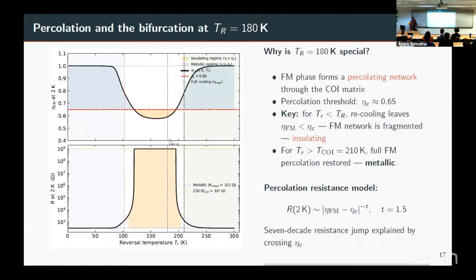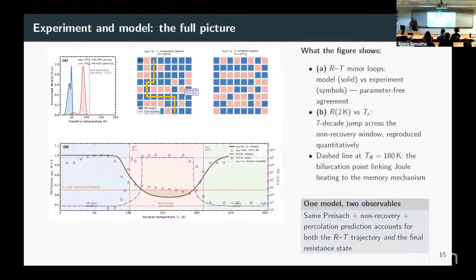So this is the behavior of the resistance at 2K obtained from the model. If I plot everything together, I get the resistance. These points here are the curve that I showed you before, the 2K resistance values. And the line is the simulation, assuming that every time you go up in temperature and come back, you have an incomplete reset of the magnetic domains. So this simple model can reproduce the resistance value and the magnetization curve at low temperature.